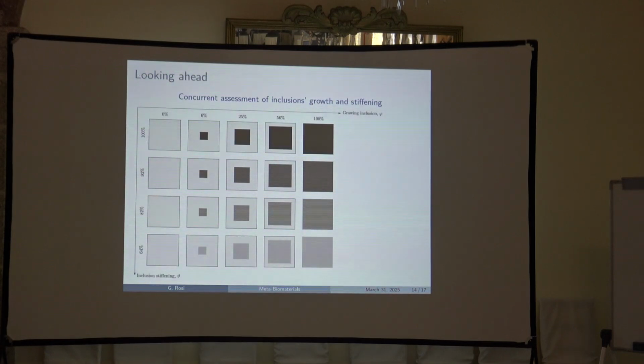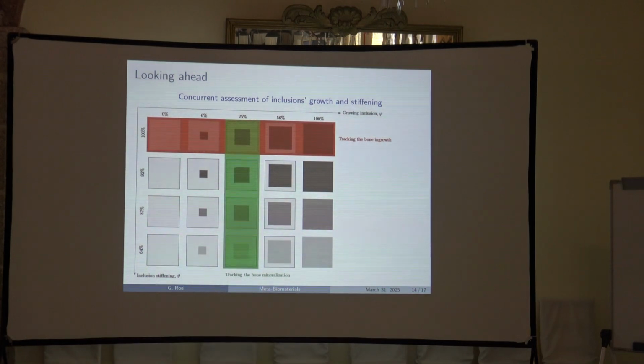So we perform this kind of test. What I showed you is the tracking of the bone ingrowth, going from this side to this side. What we've done also, but we didn't show you, is the tracking of bone mineralization, if the inclusion band becomes stiffer and stiffer. What is interesting is that one could say, okay, but basically you are going from here to here, you are lowering the overall stiffness of the implant. So you could measure these properties also from statics. I mean, with a mixture law, you can say that this is stiffer than this one, so you see that the velocity is decreasing. You can do some kind of measurement of that without needing the ultrasonic response.